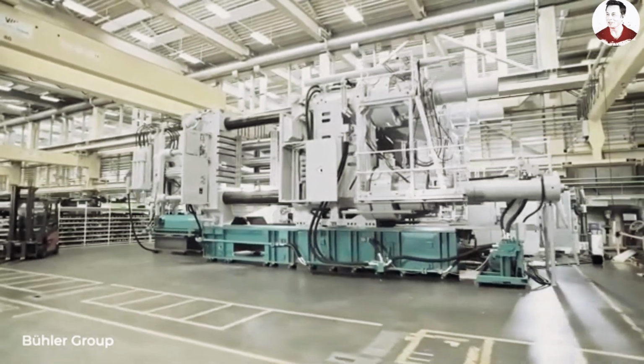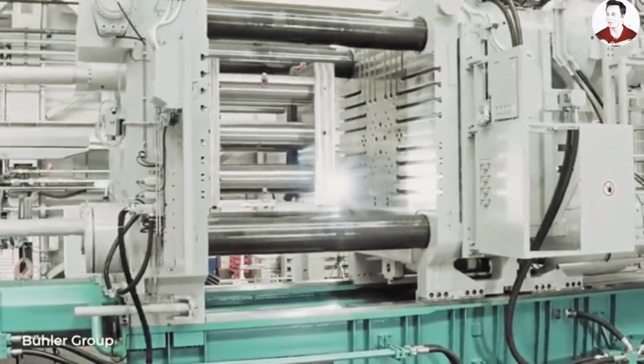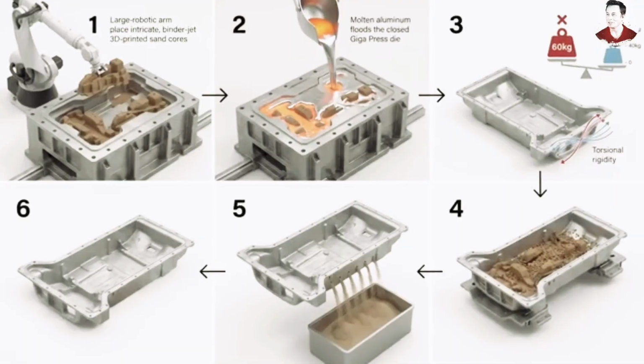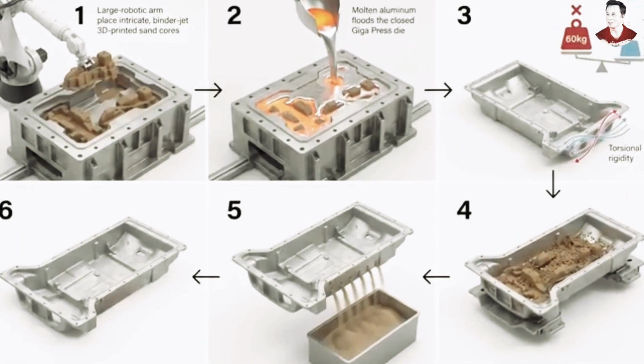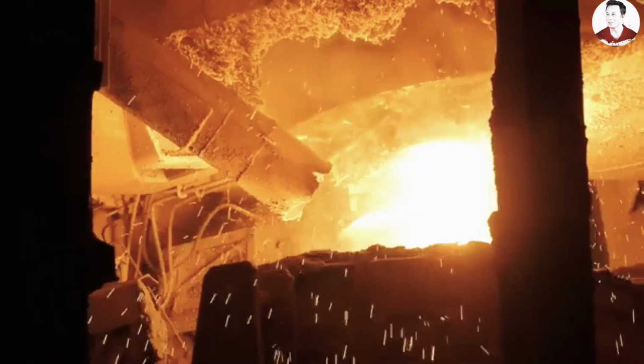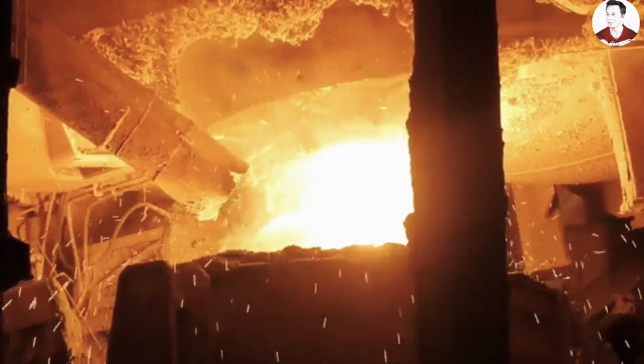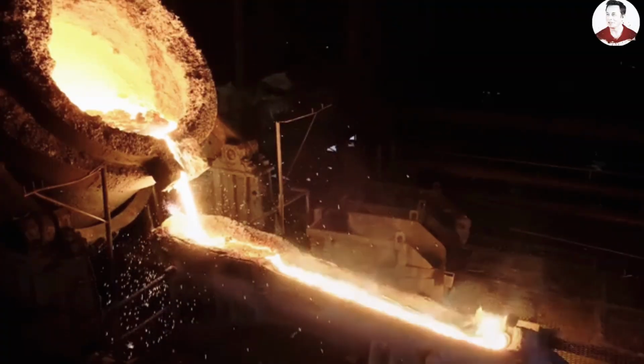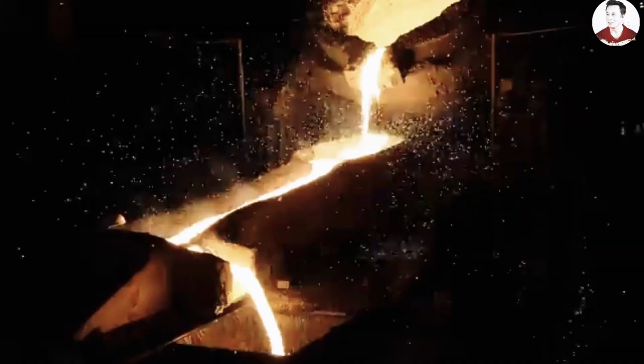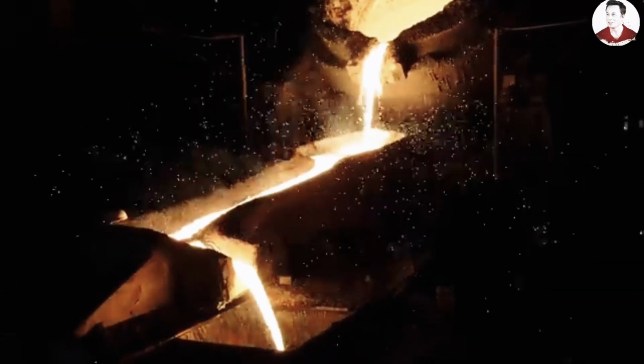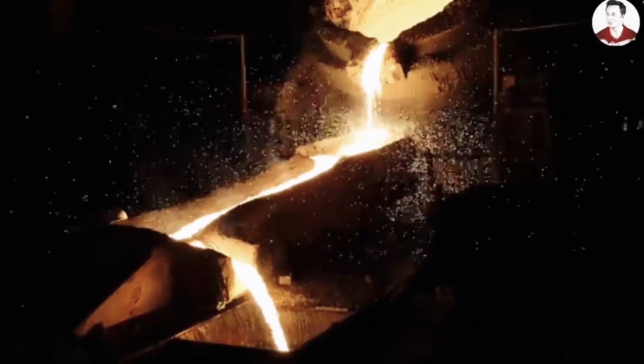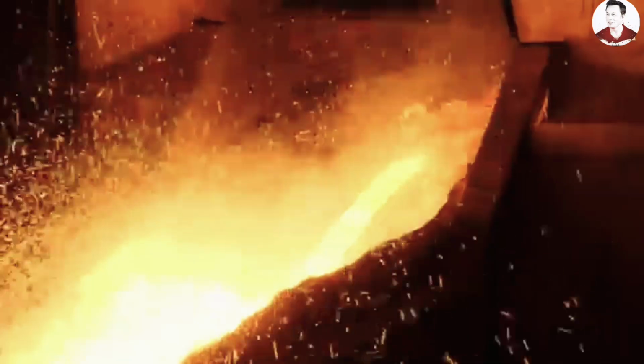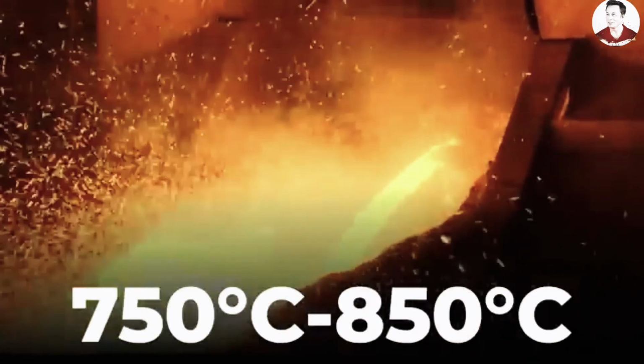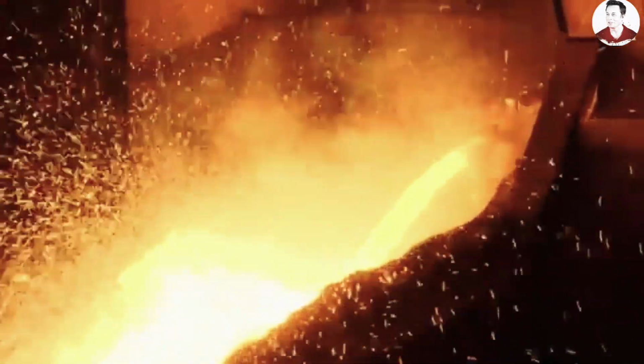Now, you might assume a 50,000-ton Giga press works completely differently from the 6,000 or 9,000-ton versions. Surprisingly, the core process remains remarkably similar. The real difference isn't the concept, it's the incredible scale and precision behind every single step. Everything starts with the aluminum. Tesla feeds both brand new aluminum ingots and recycled aluminum from previous castings into a furnace heated to roughly 850 degrees Celsius. Once the metal has completely melted, surface impurities are removed before the liquid aluminum travels through heated pipelines into a second sealed holding furnace, where it's kept between 750 and 850 degrees Celsius to ensure it's always ready for the next casting cycle.